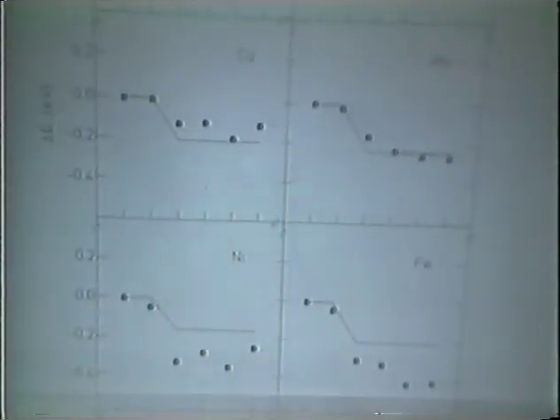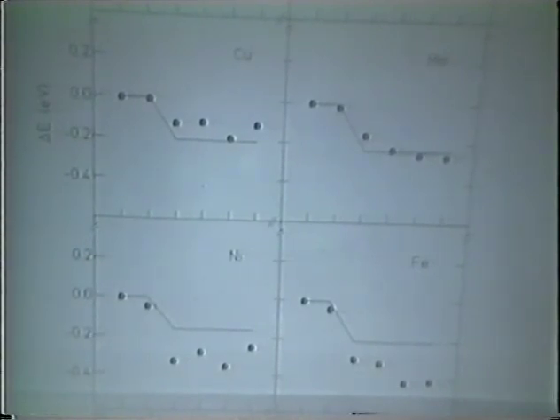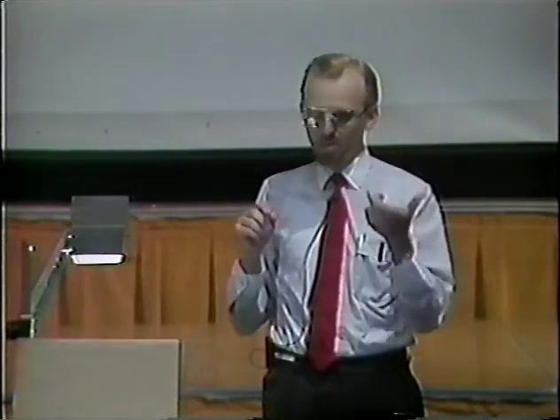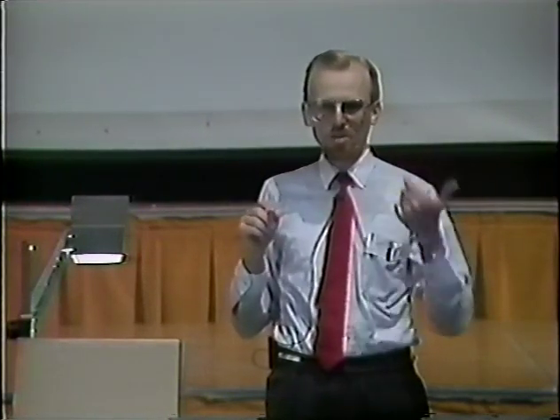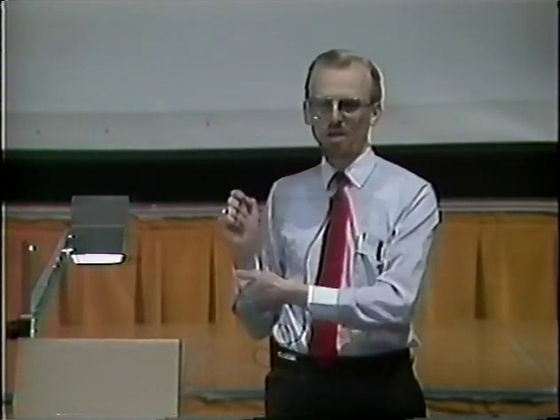The solid lines here are in fact the results from the experiment. We could not in the experiments model 6 different binding energies. So what we did was we said, okay, there's one binding energy for 1 or 2 hydrogen in a vacancy, and then there's another binding energy for 3 to 6 hydrogen in a vacancy.